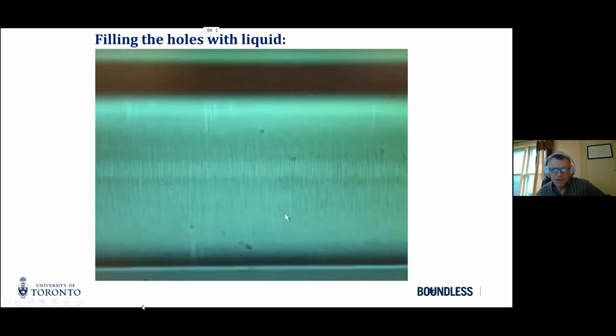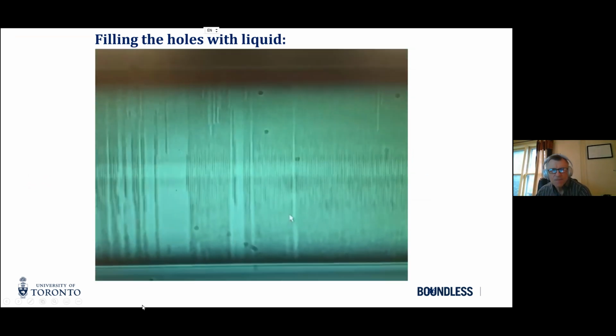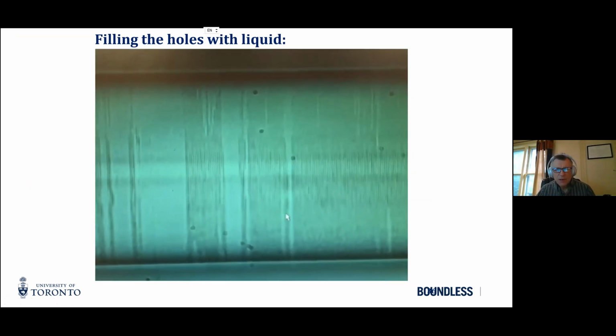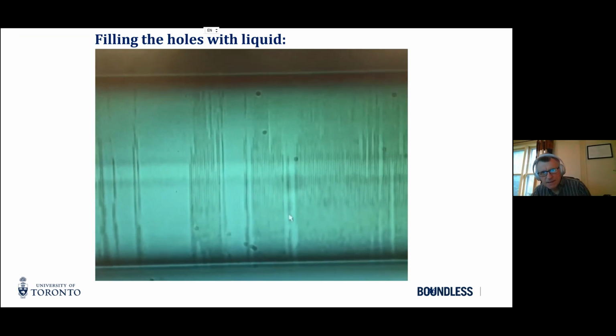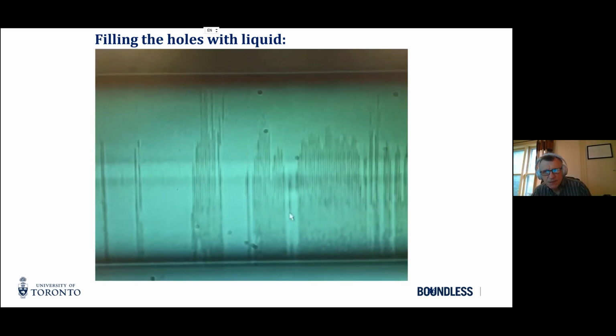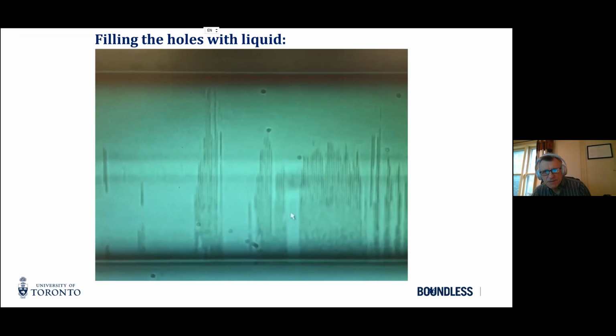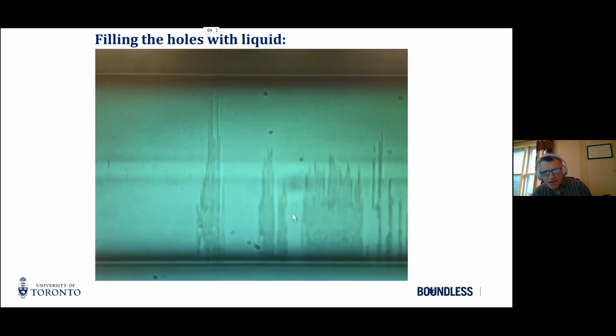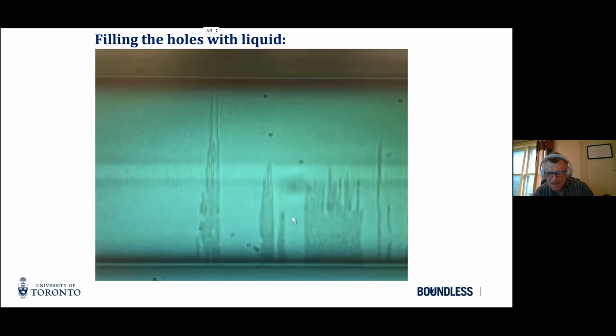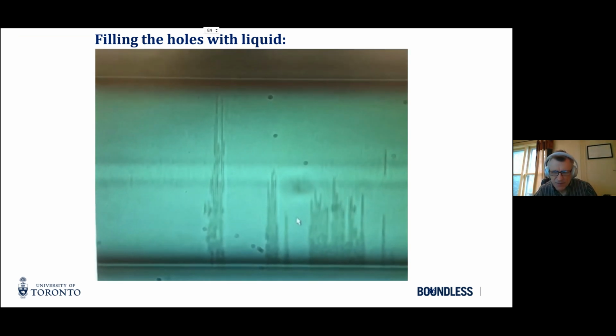Okay. So what you're seeing here is a fiber drawing by capillarity liquids into fill the hole. So the contrast goes down. So you could actually erase the gratings with index matching oils. And so they indeed do fill very well.